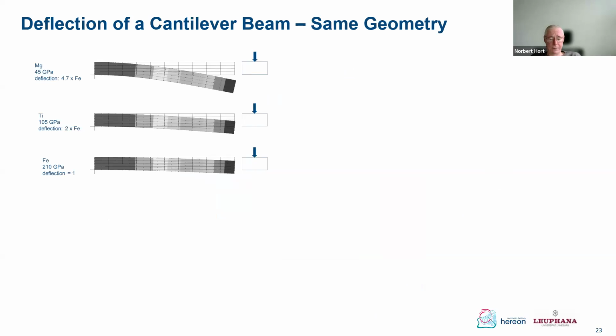And then you see there's a simple fact. You have more than 200 gigapascal for the iron Young's modulus. You define that's deflection factor 1. And you see that's 45 gigapascal, 1/5 of the Young's modulus you have for the iron, and you have 5 times the deflection. And now again, it becomes interesting, because when you convert that to a new orientation, you simply move it by 90 degrees, you still have the same relation, 5 times the deflection of iron. When you compare this geometry with this geometry, the cross-section area is identical, but the deflection is minimal compared to this one. So it's about geometry.